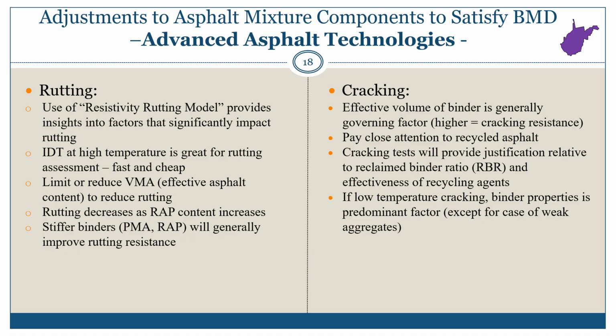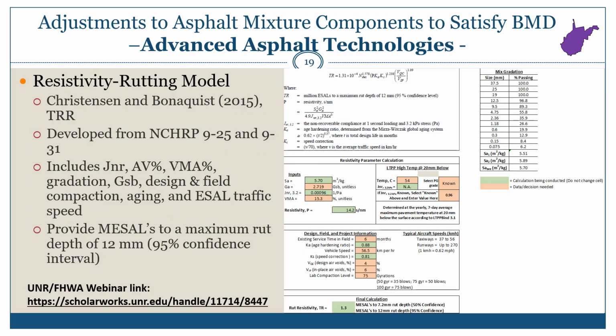A little recycling agent may be good, but too much can be detrimental to the rutting side. And also, if a low temperature cracking performance test is required, the binder properties usually will be the predominant factor. In this case, if you have a better low temperature binder PG grade, that will give you better low temperature cracking performance.